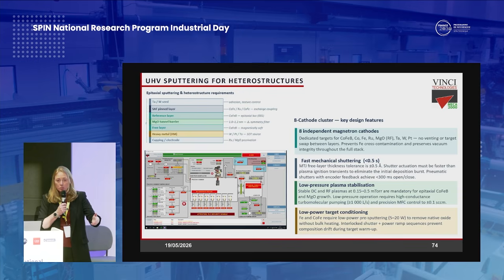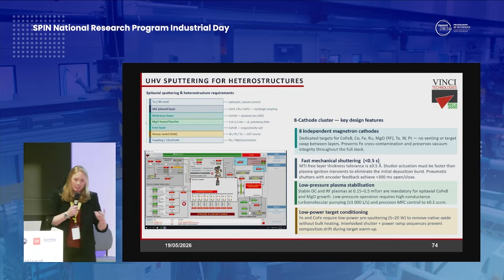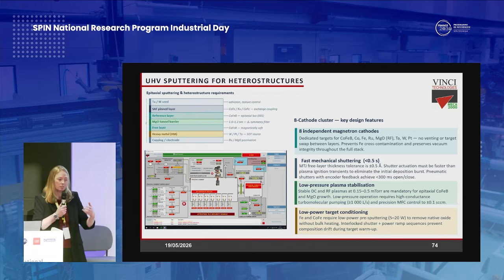For example, in terms of sputtering, when you're doing epitaxial sputtering, it is interesting to see how to integrate RHEED into the actual PVD system. That is not something that is easy to do, obviously because of the magnetic field. And then in addition to that, if you want to play with the magnetic field of your magnetrons in order to be able to grow cobalt or cobalt iron interfaces, you also have to play a little bit with the balanced unbalanced effect of your magnetrons.